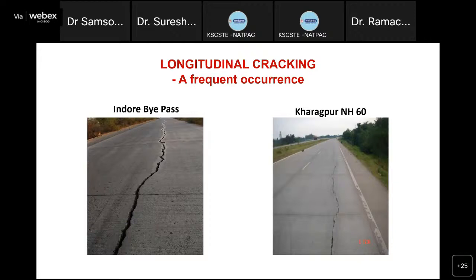Now, longitudinal cracking: in recent times, in a lot of our highways, we are seeing this longitudinal cracking. Indore bypass is one example. In fact, when we were doing our white topping work in Kharagpur, we noticed this on the national highway NH60. Longitudinal cracks very close to the shoulders. This was observed, and the length of this crack goes up to 1.5 kilometers. Longitudinal cracks, they continue to be there.